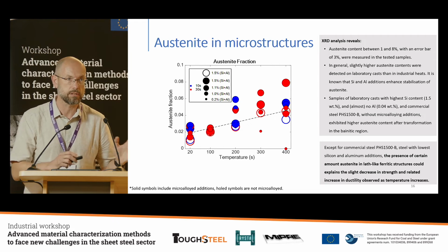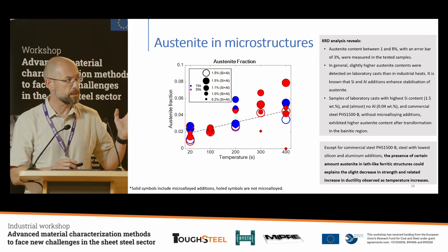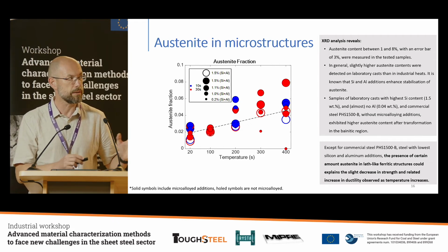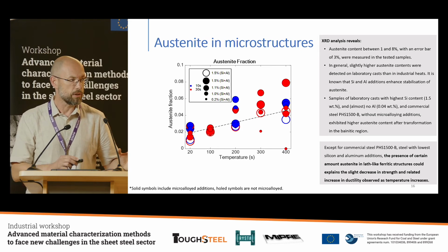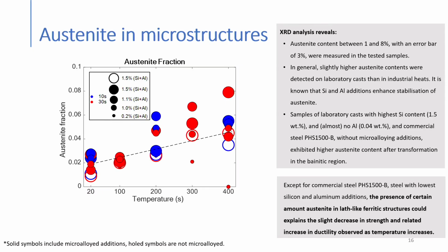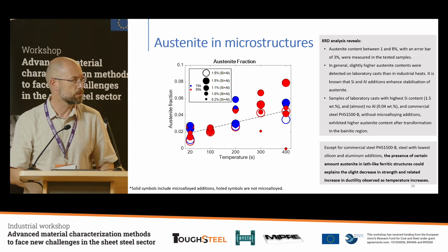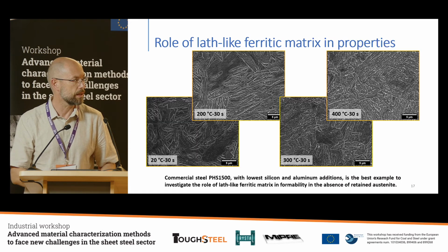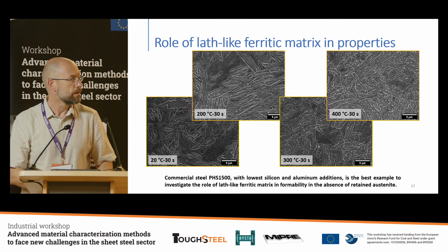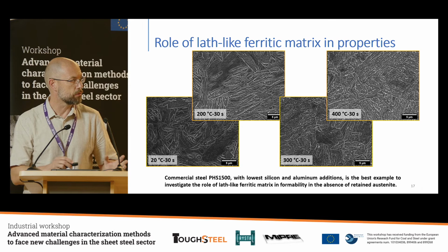Because if you observed in the previous slide when I mentioned the difference in the scheme, when you have two phases, all the results can be distorted by the presence of the second phase, which is very difficult to control. So when you avoid this second phase, it's easier to control the microstructure. So here, for example, are the microstructures obtained at the different tool temperatures, from room temperature to 400 degrees C.